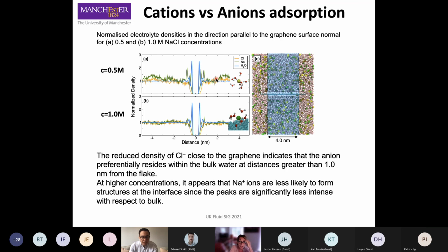And these are results for uncharged graphene. And we look at basically if the ions are on the surface or not, and what is the effect of the concentration of the electrolyte. So what we saw is that basically, because here there's the graphene, what actually is in direct contact with the graphene is always water. The ions do not dehydrate completely. So sodium is the one that is closest to the surface of the graphene. The anion, as we expected, is much further away, but the amount of ions that are totally dehydrated is very tiny.